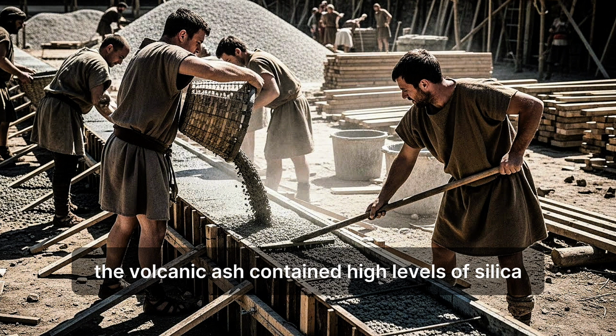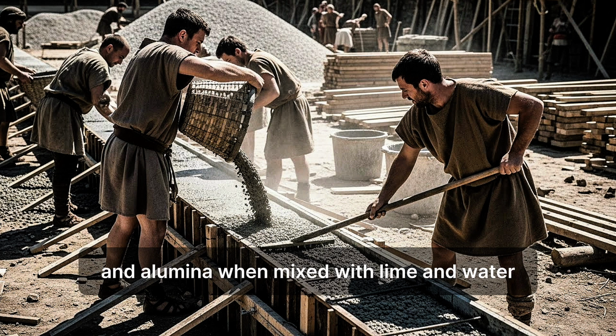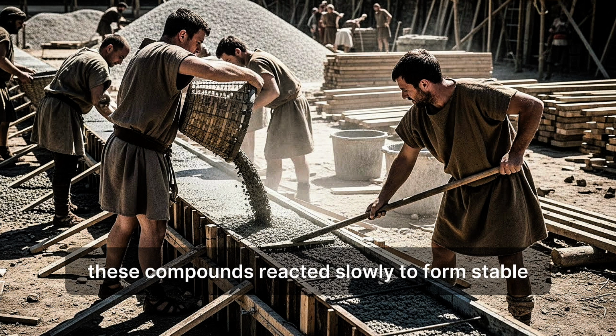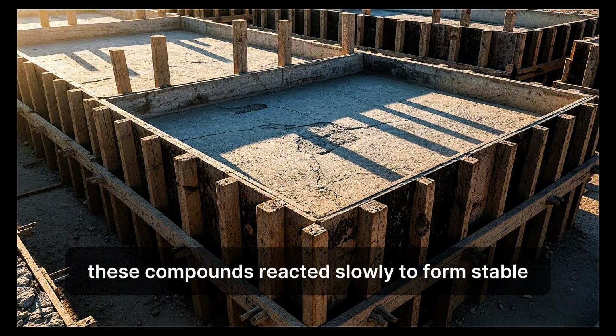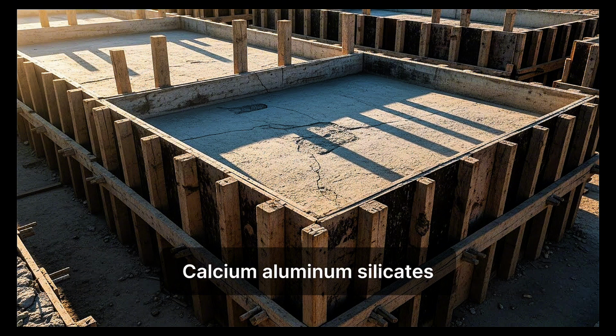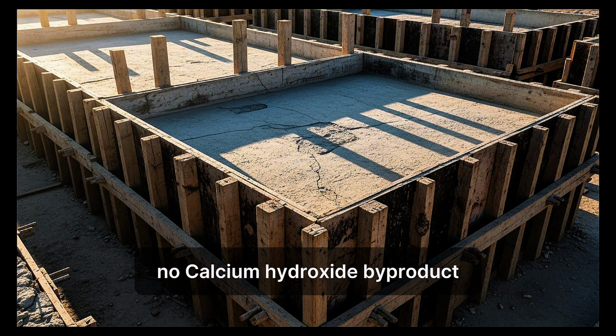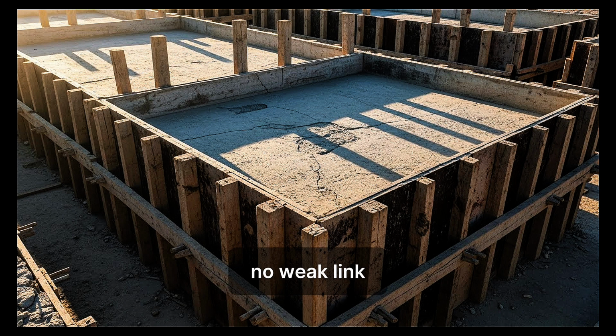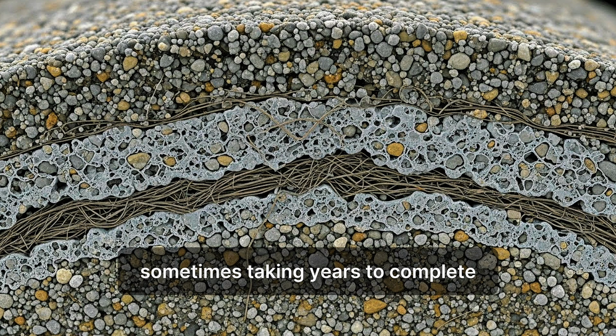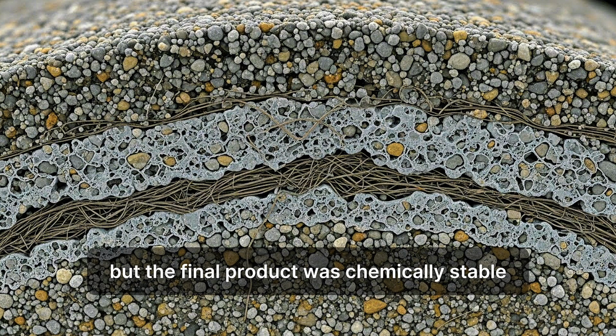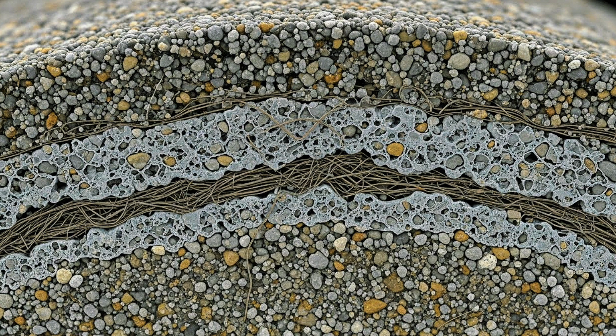The volcanic ash contained high levels of silica and alumina. When mixed with lime and water, these compounds reacted slowly to form stable calcium aluminum silicates. No calcium hydroxide byproduct. No weak link. The reaction was slow, sometimes taking years to complete, but the final product was chemically stable and resistant to attack.